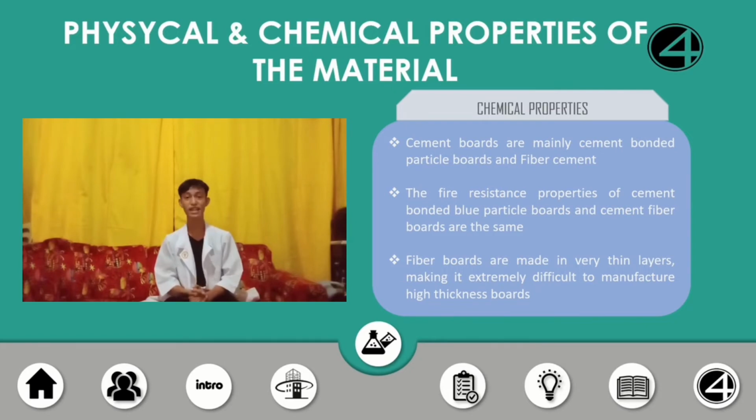Many manufacturers use additives like mica, aluminum and stearates, and cenospheres in order to achieve certain board qualities. A typical cement fiber board is made of approximately 40 to 60% cement, 20 to 30% fillers, 8 to 10% cellulose, and 10 to 15% mica. Other additives like the above-mentioned aluminum stearates and PVA are normally used in quantities less than 1%. Cenospheres are used only in low-density boards with quantities between 10 and 15%. The actual recipe depends on available raw materials and other local factors.